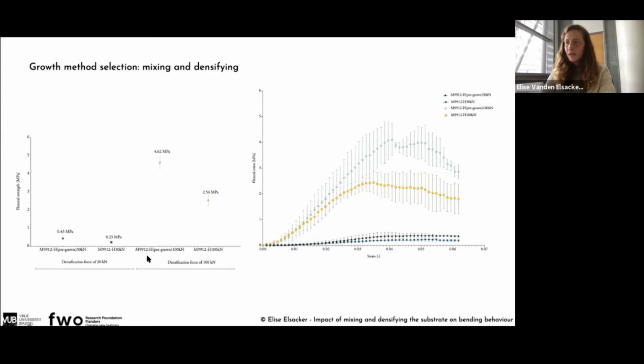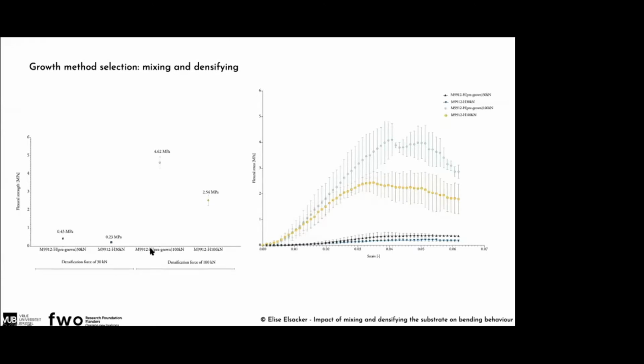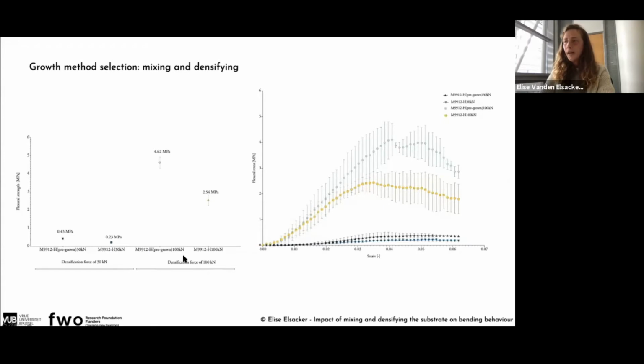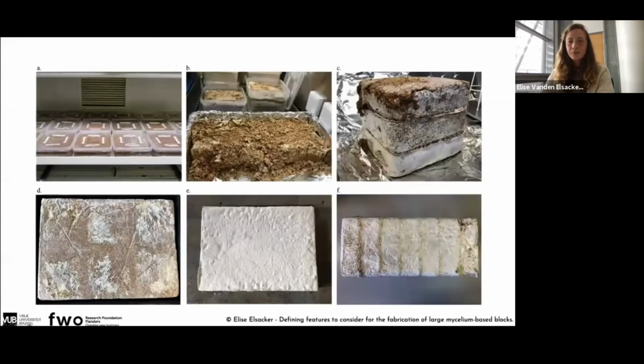From the bending test that we did with different types of samples here, we have pre-grown samples in the bags, and samples that were made directly in the molds. And then I also tested different compression, densification forces on these materials. So you can see that the mechanical properties enhance quite clearly when samples are pre-grown, which was kind of expected, but it's always nice to see it in a graph.